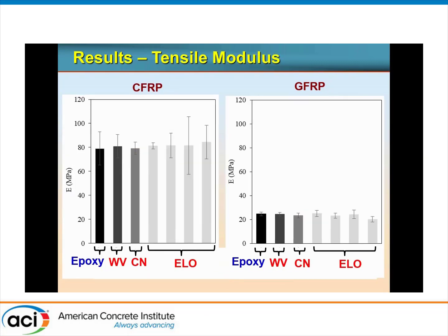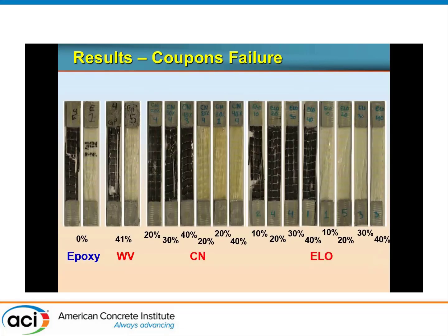In terms of the modulus, essentially no difference. You see the variation within the Young's modulus is higher than the strengths because it's a bit sensitive to the extensometer and so forth to get the Young's modulus, and localized damage and so forth. But essentially no major effect on the Young's modulus of the coupons. Same with failure modes. We did not particularly correlate any particular mode of failure of the coupons with the type or percentage.